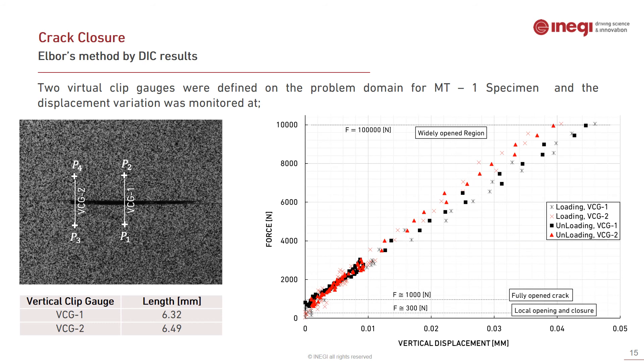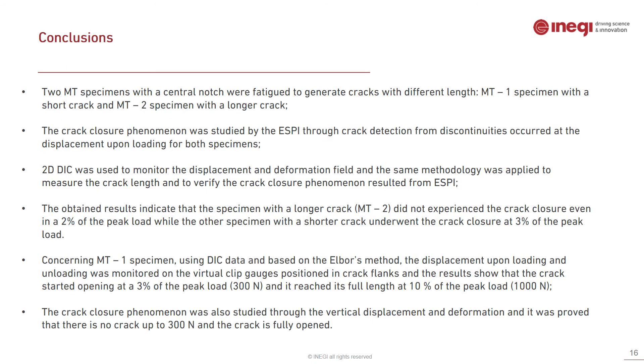Regarding the Elber method, two virtual clip gauges were considered on the crack flanks, and the displacement upon loading and unloading was monitored by Digital Image Correlation. Displacement discontinuities and deformation are evidenced here: at 300 N there is local opening and closure; once we reach 1 kN the crack is already fully open; and when approaching 10 kN, this is the widely open region.